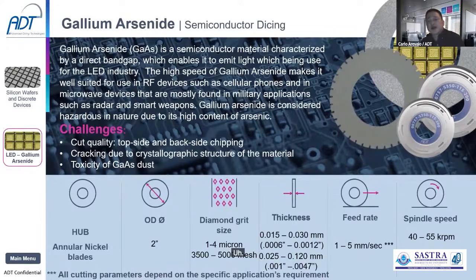Diamond grit size can range from 1 to 4 micron or 3500 to 5000 mesh. Thickness is from 15 to 30 micron, or 25 to 120 if you're using a hubless blade. Feed rate is relatively low at 1 to 5 mm per second. Spindle speed, again, is dependent on what blade or diameter you're using.